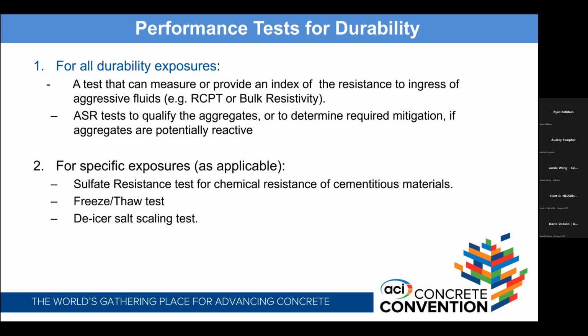And of course, you need tests to qualify the aggregates to make sure there isn't going to be an alkali silica reaction, or if you are going to use reactive aggregates to determine the required mitigation measures. And then, of course, you have specific exposure requirements for sulfate resistance, if it's applicable, freezing and thawing, if you're in that environment. And of course, related to that is de-icer salt scaling. So you have applicable test methods that come in and requirements based on the applicable exposure.